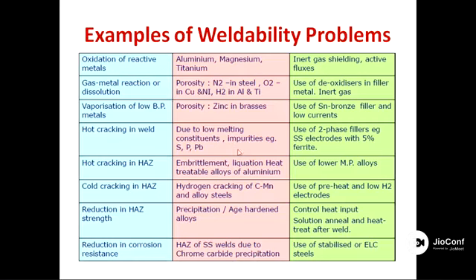Then the hot cracking issue. This is the main issue with austenitic stainless steel, and it is because of the presence of some low melting constituents or impurities like sulfur, phosphorus, or lead present in a hot or molten metal. So these low melting constituents are not freezing at the temperature at which the rest of the metal is freezing, right? They are freezing very last.